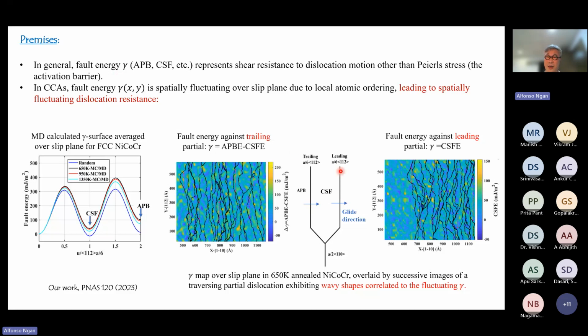For the case of the leading Shockley partial, as I said, the complex stacking fault would be the main resistance. In the case of the trailing, when the trailing dislocation marches forward, it annihilates the complex stacking fault, but it generates an antiphase boundary, in the case of an alloy where ordering could happen. So in this case, the effective value of the fault energy acting against the motion of the trailing partial would be the APB energy minus the CSF energy. So that would be the resistance for the trailing. For the leading, it will be just the CSF energy alone. So it is either the CSF or the APB minus CSF fault energy, representing the shear resistance to Shockley dislocation motion other than the Peierls stress.